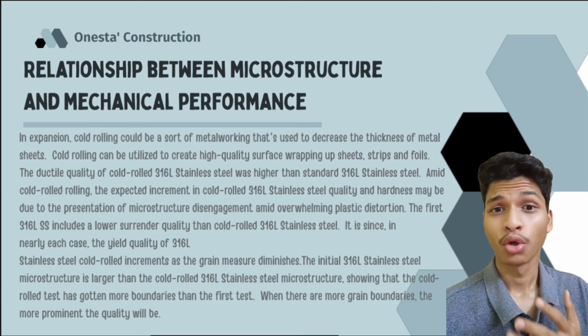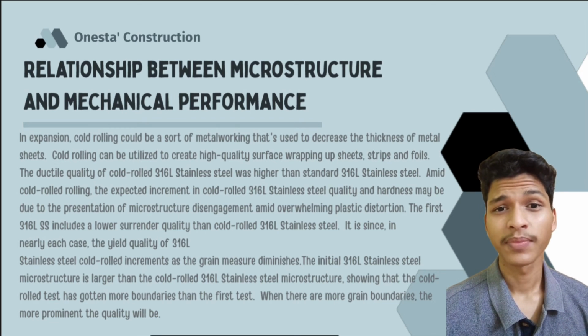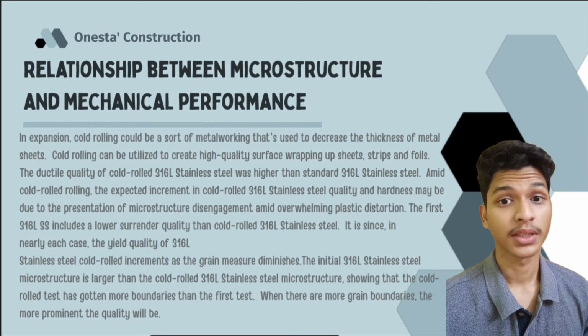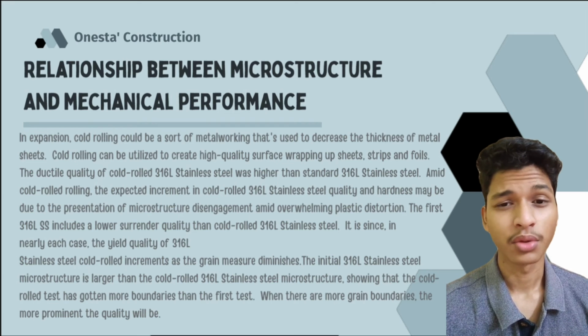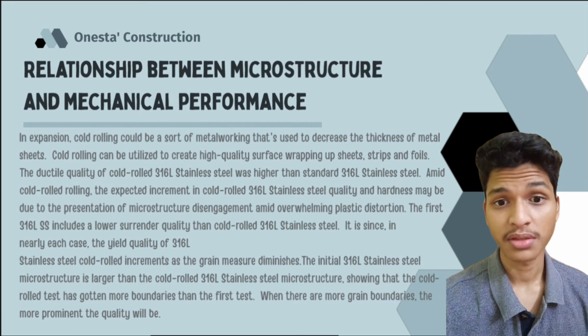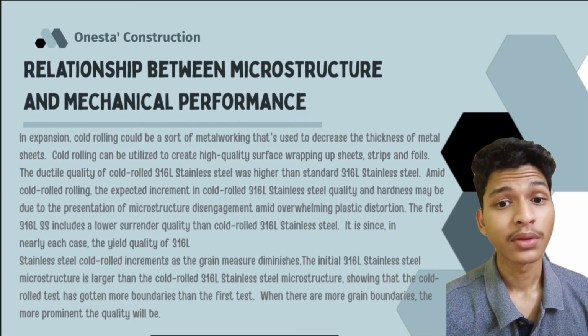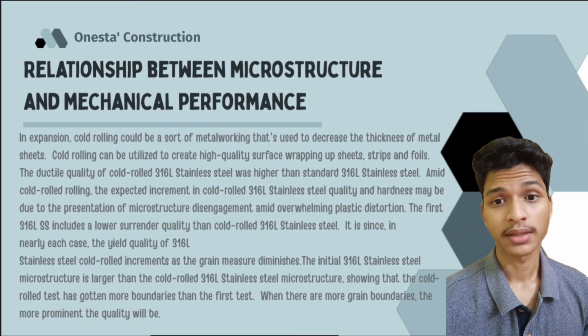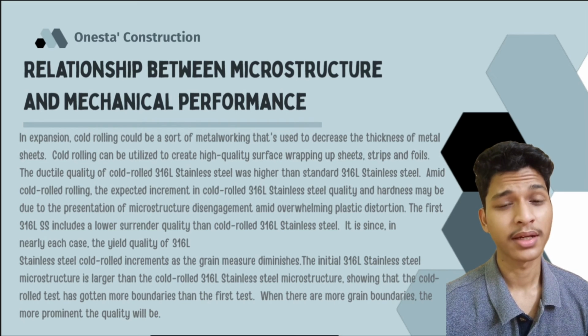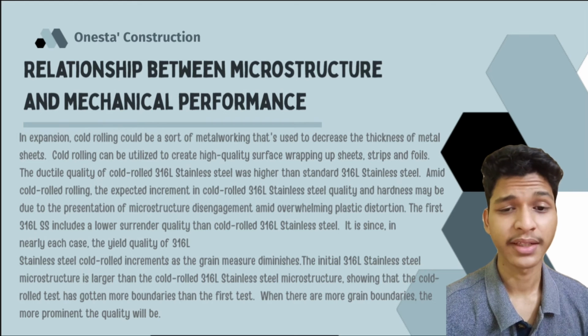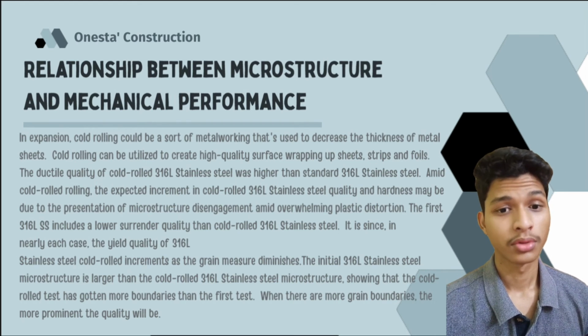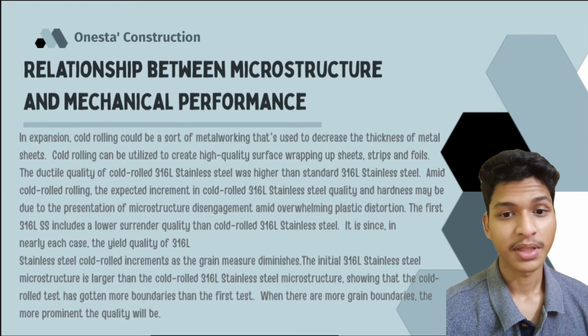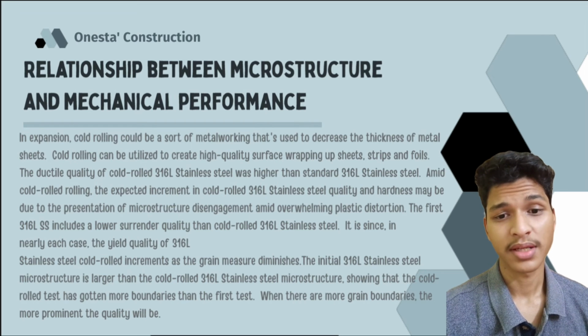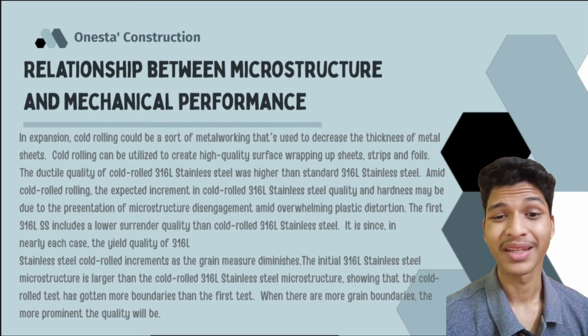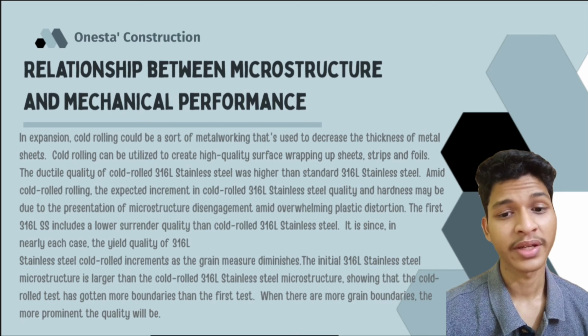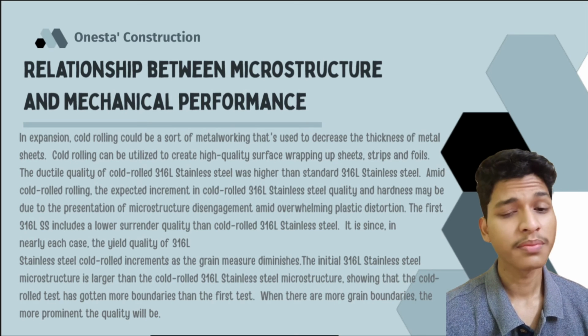In addition, cold rolling is a sort of metalworking that is used to decrease the thickness of metal sheets. Cold rolling can be utilized to create high-quality surface finishing sheets, strips, and foils. The tensile strength of cold-rolled 316L stainless steel was higher than that of original 316L stainless steel. Cold rolling increases the strength and hardness of 316L stainless steel, which may be due to the presence of microstructure dislocations and heavy plastic deformation.